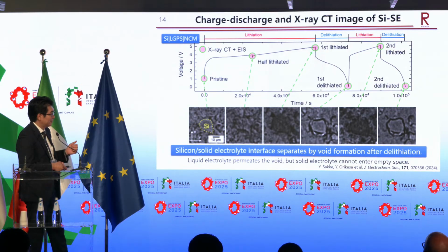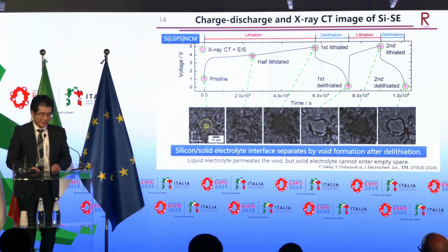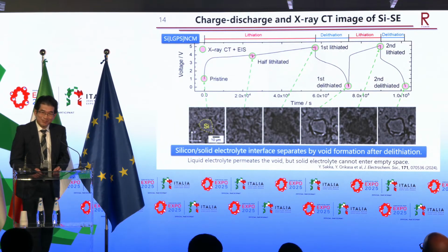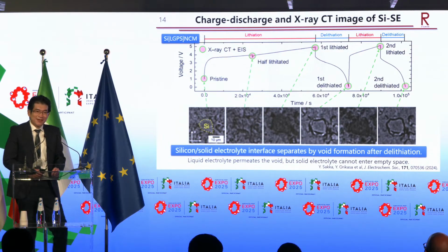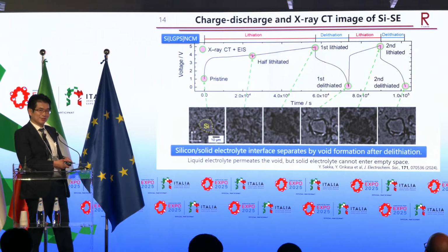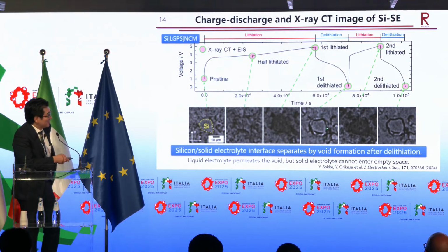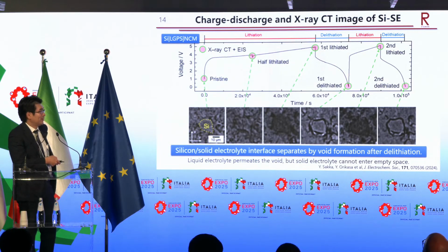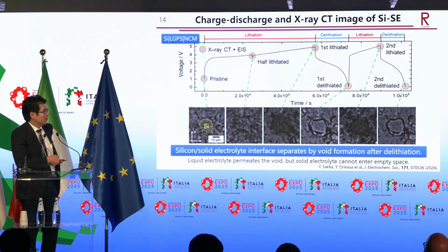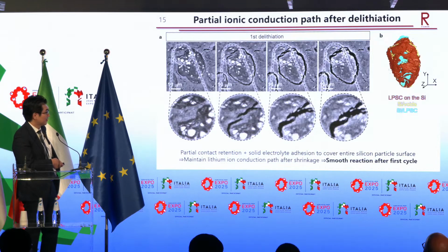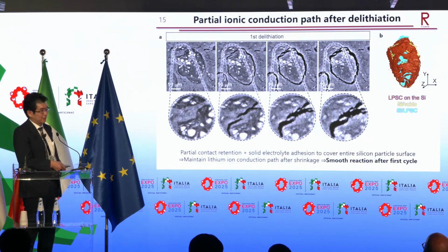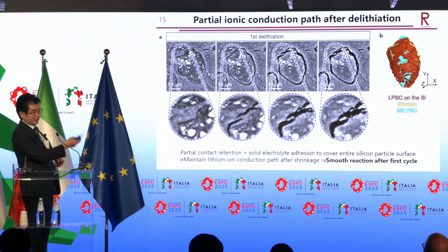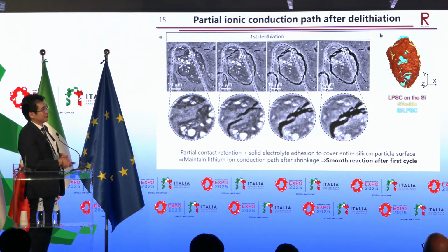When I look at this figure, actually I was disappointed, because in this case lithium ion cannot be supplied to the active material, so many of the reactions may be stopped. However, after the first charge discharge, the reaction can proceed. So what is the reason for this? When we look closely between the silicon active material and electrolyte, we know the reason why the cycling of all solid state battery can be achieved.